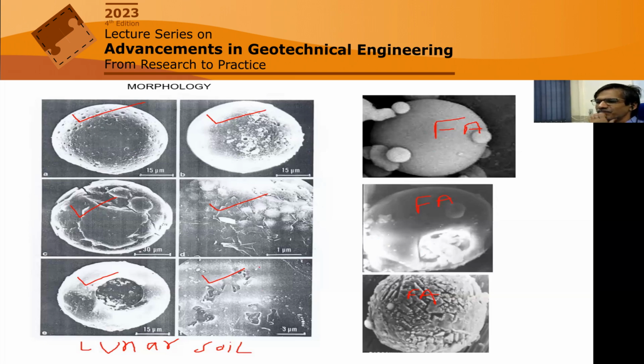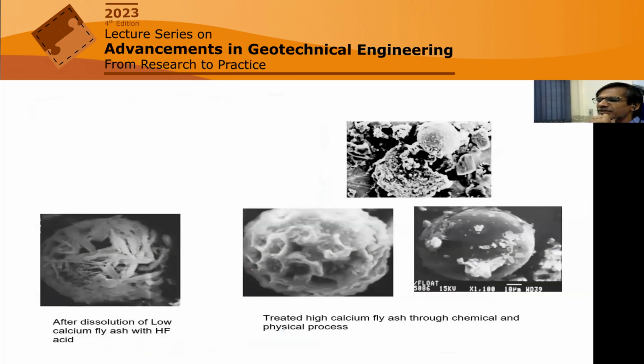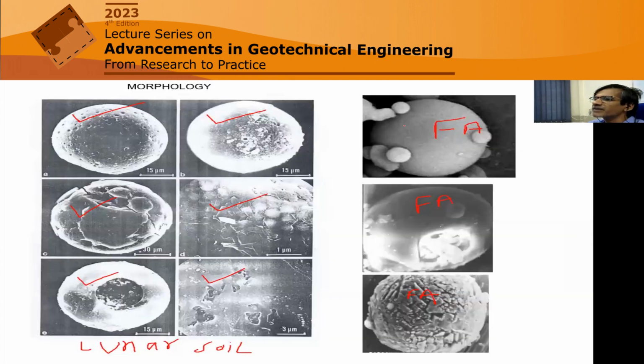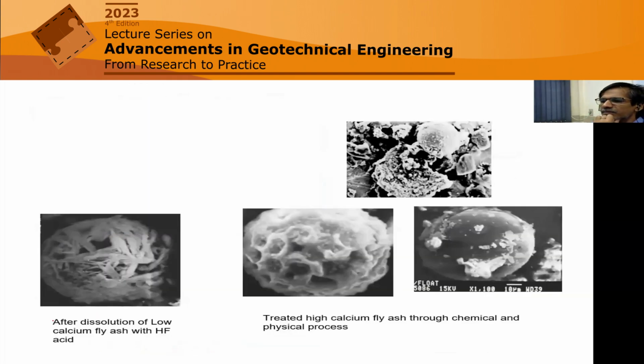Then again, for its utilization, we need to check. Because in the previous slide, if you see, the fly ash was looking very smooth surface. Here it was a rough surface, but in these two, it was a smooth surface. What are the smooth surface? In one of my investigations, I had dissolved it with hydrofluoric acid, which will tell that it is mostly aluminosilicate. Inside, if you see, there is again a good structural spherical form on which the skeletal aluminosilicate glass was there.